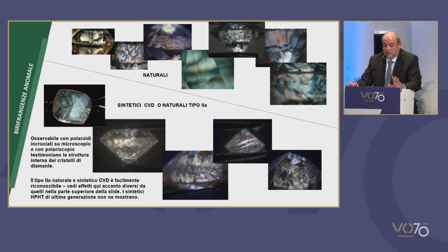So synthetic CVD diamonds, and also sometimes natural diamonds, but please consider that these natural diamonds are very rare, can have these characteristics, which, however, are very stiff. Americans call them tatami, which recall the Japanese fabric. So they are either cross or linear. Again, you have to have a bit of experience, but when you see these figures, well, it's a bad sign, so to say, because you need further controls.